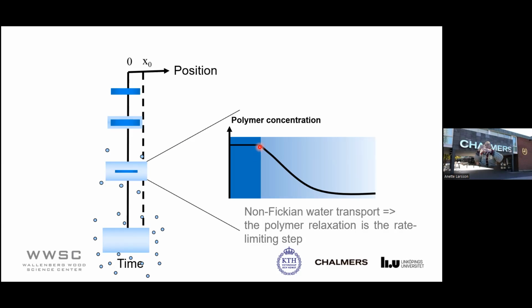And then we have a transition of the polymer going from a glassy state to a rubbery state. And in the rubbery state, it is much more flexible and it can expand much more. So the relaxation time here is when it goes from glassy to the rubbery state. That is the rate limiting step. This means that this core diminution is not controlled by the classical diffusion controlled water transport. It is instead non-Fickian transport. And that is what we call polymer relaxation is the rate limiting step.